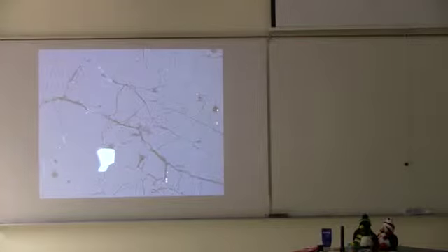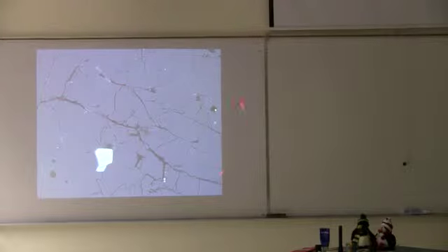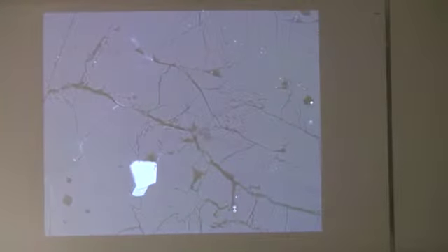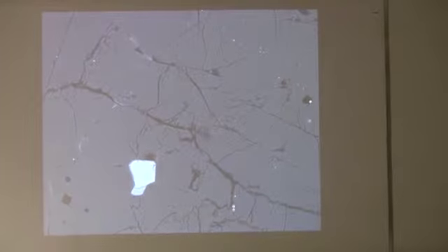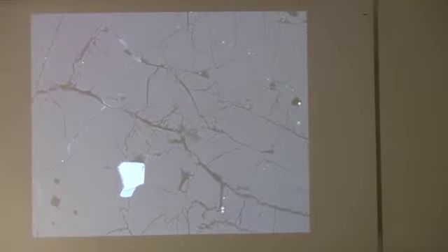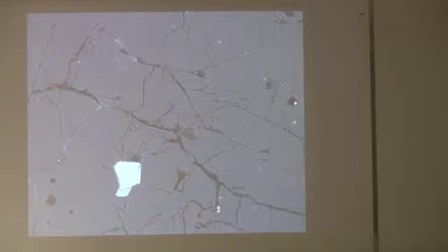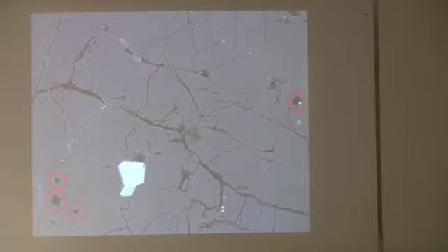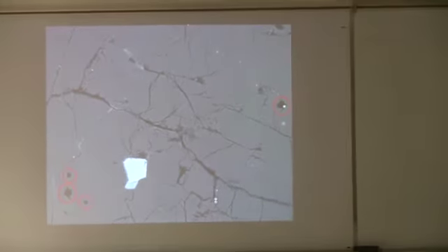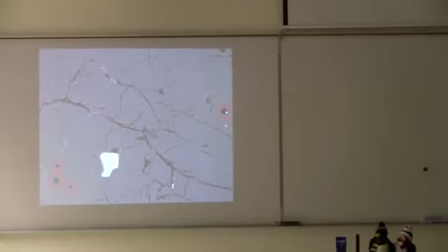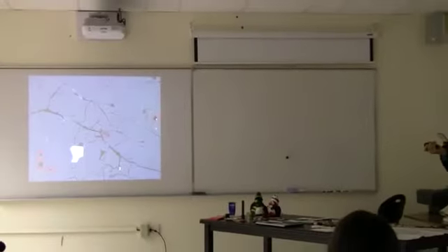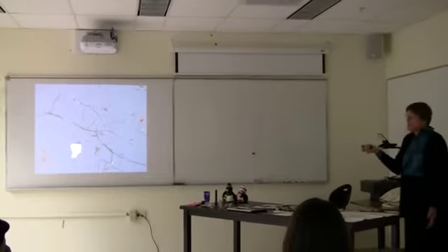So I went back and looked at those. And I say, okay, here's a piece of some enstatite chondrite. And I got to looking at this and I went, idiot. You're the one that did your PhD thesis on enstatite chondrites. And all these little holes here used to have oldhamite in them. And oldhamite is a water-soluble mineral that holds all the rare earth elements, which was what I was analyzing, but it's water-soluble. They've been sitting in a drawer in Michigan with high humidity, and the oldhamite's gone.